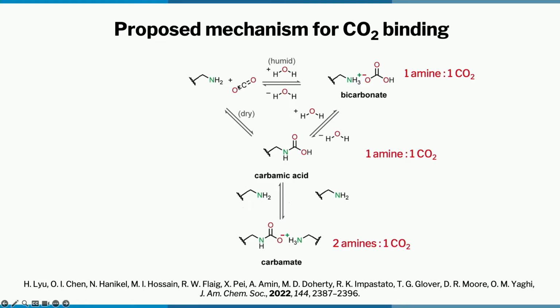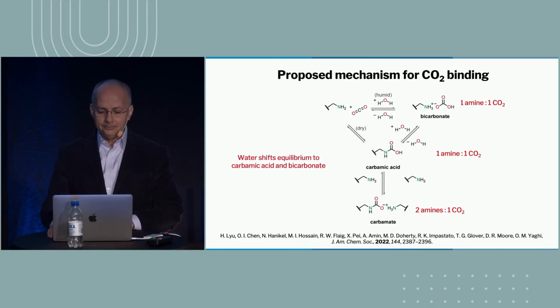And what it's doing is when it's humid, you make bicarbonate, and you also make carbamic acid. But when you don't have humidity, when there is no water, you make carbamate. So with water, you're shifting the equilibrium to carbamic acid and bicarbonate, and luckily, that's better than when it's dry. When it's dry, you need 2 amines for each CO2, so you need double the amount of material. When it's wet, you only need 1 amine per CO2. So we are very fortunate to find that this is the case.